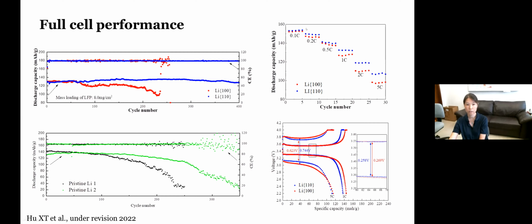Then we'll also look at the rate performance of the cells. In comparison with the lithium-100 and the lithium-110, we see the two cells are similar, actually, at low rates. But if you increase the rate to 5C, the difference between the two becomes obvious. And we also show the voltage hysteresis at low rates, right? The behavior of the lithium-100 and 110 is very similar, but then we increase the rates to 5C. The hysteresis of the lithium-110 is smaller, right, than the 100.